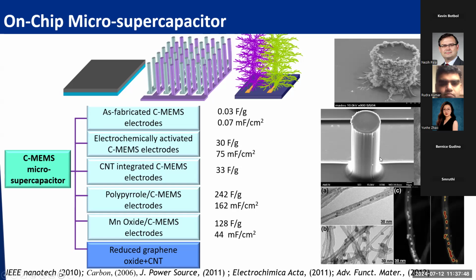But if we coat the catalyst directly on the glassy carbon post, not during the carbonization process but after carbonization, then we can put this carbon post with the catalyst into the CVD chamber. We can grow carbon nanotubes directly on the carbon post. And another research, you can see at the bottom, A, B, C, D, those four figures, we actually can add manganese oxide nanoparticles directly into the carbon nanotube. So that's a composite. We have both a double layer capacitor based on carbon nanotube and the manganese oxide-based pseudocapacitor material inside the carbon nanotube. And it's very well nano-confined because they are inside the carbon nanotubes.